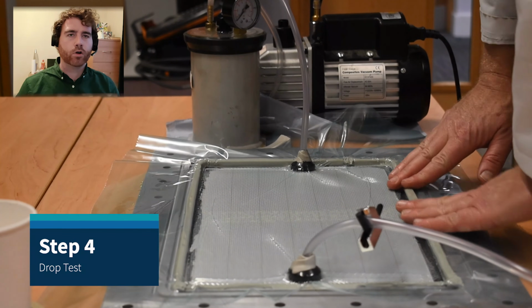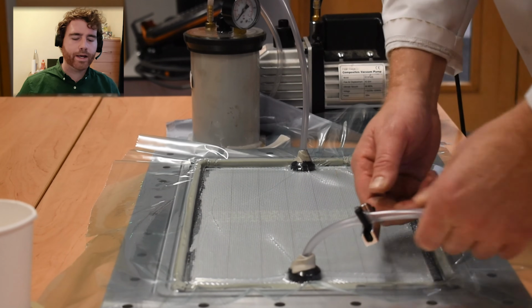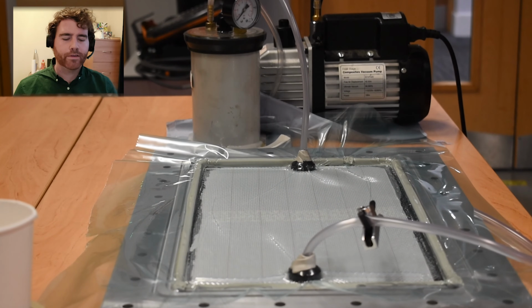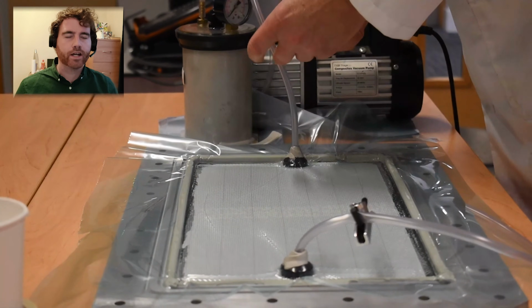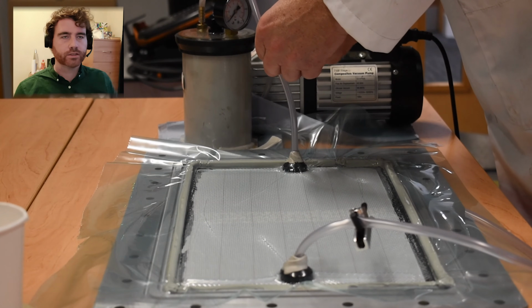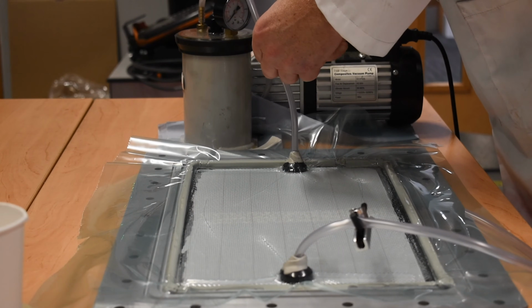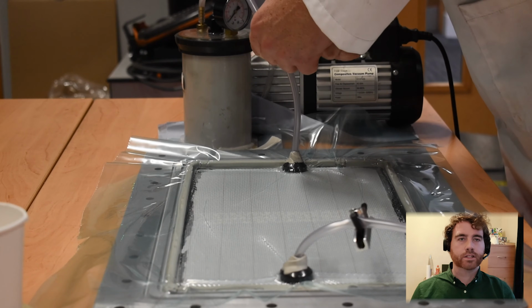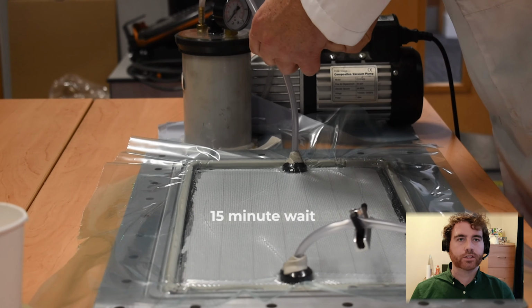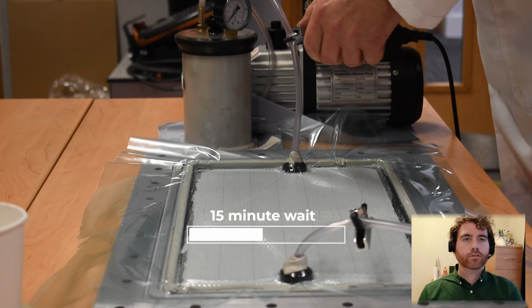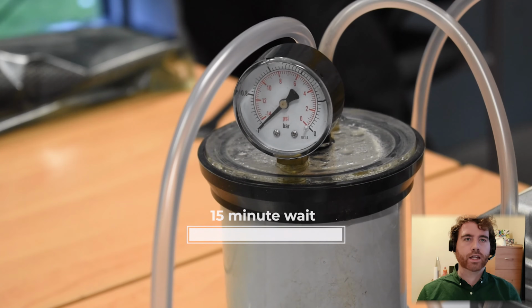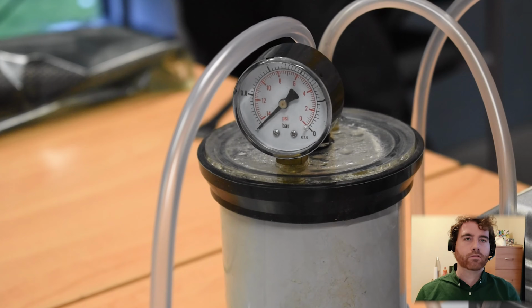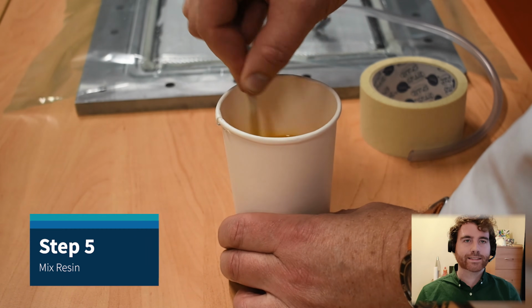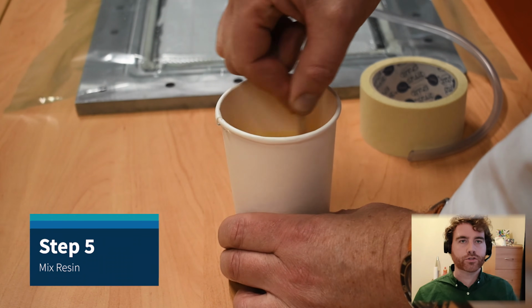The drop test is performed by pulling a full vacuum on the bag. The bag is then clamped off and the gauge is used to check if there is any drop in vacuum. This would indicate a leak during the process. We're waiting 15 minutes here to ensure that there are no leaks and no change in pressure. After 15 minutes there's been no change on the gauge, so we're still holding 1 bar of vacuum. So we have no leaks at this stage, so we can continue with our infusion.